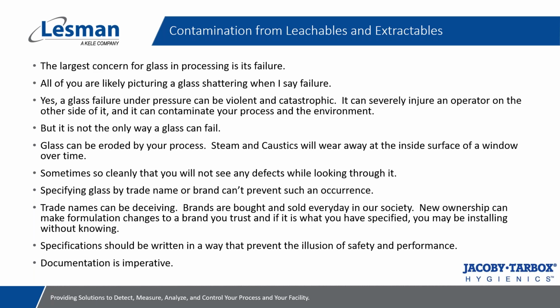If you're putting windows into your process and they are not a USP type 1 borosilicate, and then you are interacting with them through steam cycles and cleaning cycles, you are leaching the elemental properties of those windows. Most of them are made out of soda lime glass. Soda lime glass is the most common glass in the industry.